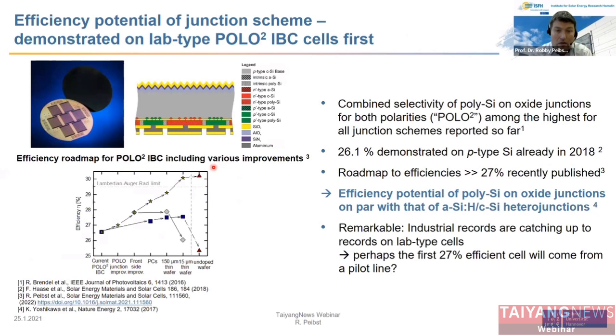And you can also try to fabricate record devices, for example, on lab level first. And this is what we have done already in 2018, presenting an efficiency of 26.1% on this IBC structure here. Quite recently, we have published a paper showing a roadmap for how we can get this technology to efficiencies above 27%, with some improvements on the passivation quality, but also on the optics. That means that we are convinced that the efficiency potential of this polysilicon oxide junction is on par with that of the silicon heterojunctions and is above 27% for this IBC structure at least.